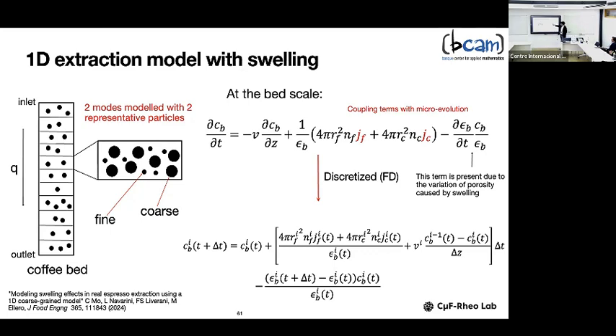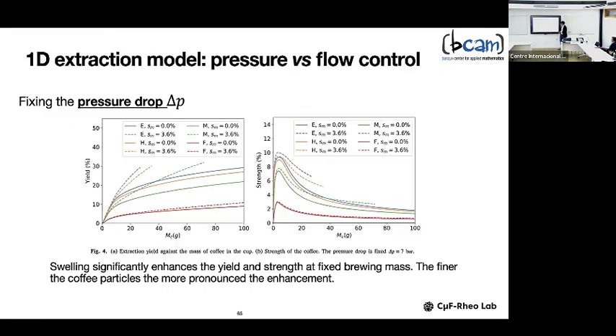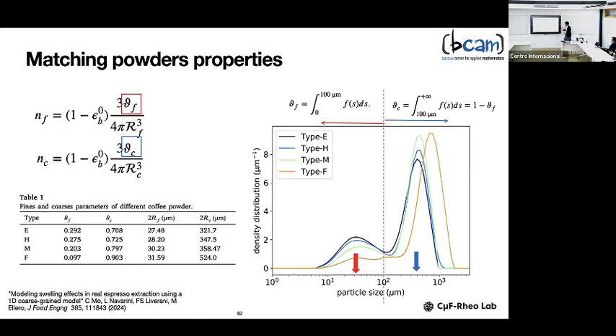The way in which we discretize this equation is by finite difference. The only important thing is that we can characterize different powders simply by looking at the typical radius of the fines and the volumetric change of the fines, the radius of the coarse and the volumetric change of the coarses. You can do this very easily when you get the granulometry of different powders. You already know the peaks, so you know exactly what RF and RC are. They're just the location of the peaks.